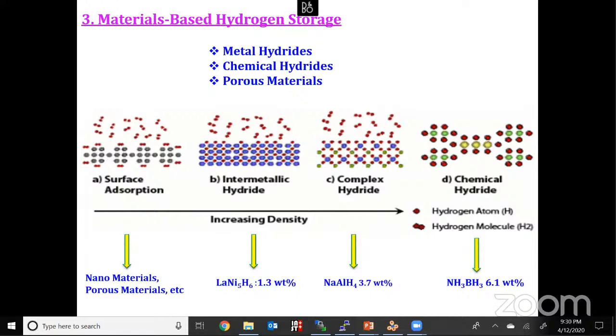Whether we can use it for repeated cycles depends on the durability of the material. From that point of view, porous materials are promising. But to get a higher weight percentage, we can use chemical hydrides, where the hydrogen molecule is broken and hydrogen chemically binds with the metal. But in that scenario, we need to give an enormous amount of energy to release the adsorbed hydrogen molecule.